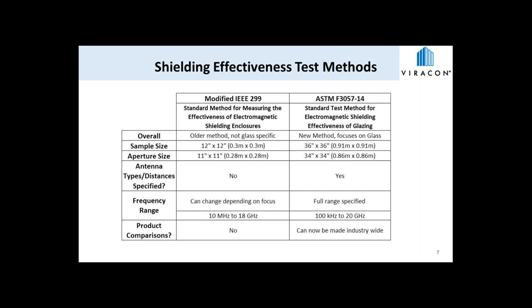Back to the IEEE modifications and moving down on the table. Depending on the test enclosure or the specific equipment at the particular facility, the antenna types and distances were often changed within the IEEE method, whereas in the ASTM method, they are called out. Frequency range, moving down, was another portion of the IEEE method that was often changed, depending on the specific focus of the individual company or the individual building requirement. So for the ASTM method, the frequency range is called out and is actually extended to include the lower wavelengths. Overall, though, by standardizing the test method for glass, product comparisons can now be made industry-wide, really giving customers more confidence that the product selected will perform as it did in laboratory testing.